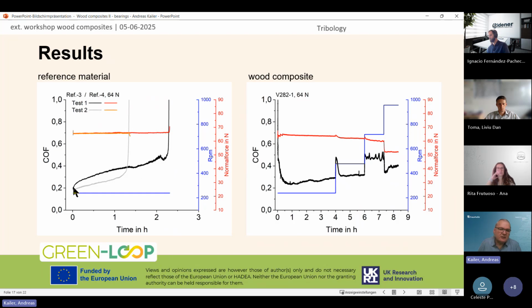They started at 0.2 and continuously increased to values above 0.4. And at a certain point, we got catastrophic failure because the friction was so high that the thermal temperature increase was too high for the material, and it melted down, and the test stopped already before the next